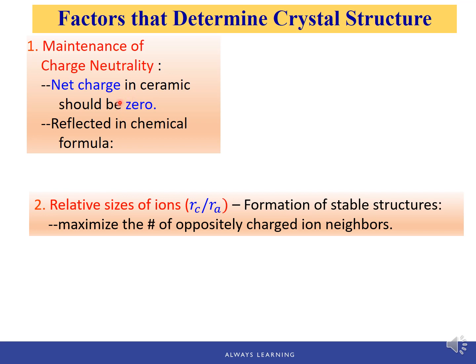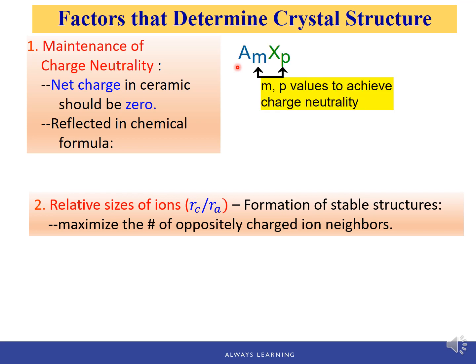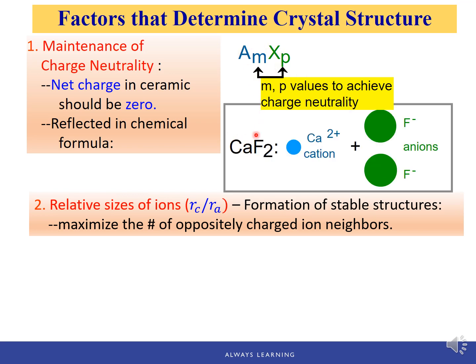So all the cation positive charges must be balanced by an equal number of anion negative charges. The chemical formula of a compound indicates the ratio of cations to anions, or the composition that achieves that charge balance. So m and p are the number of cations and anions respectively, and those values should satisfy charge neutrality for this compound. For example, in calcium fluoride, each calcium ion has 2 positive charges, and each fluorine ion has a single negative charge. So there must be twice as many fluorine ions as calcium ions, which is reflected in this chemical formula: CaF2, one calcium ion associated with two fluorine ions to achieve charge neutrality.